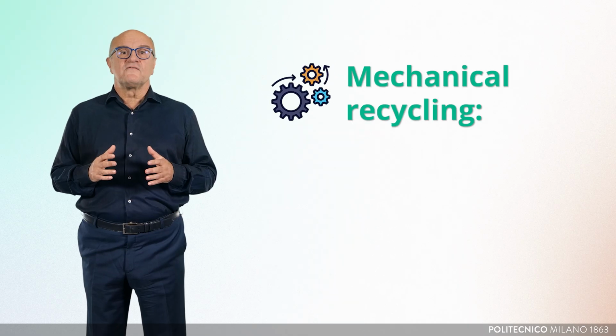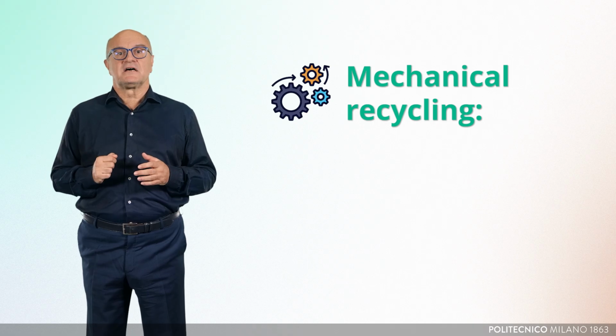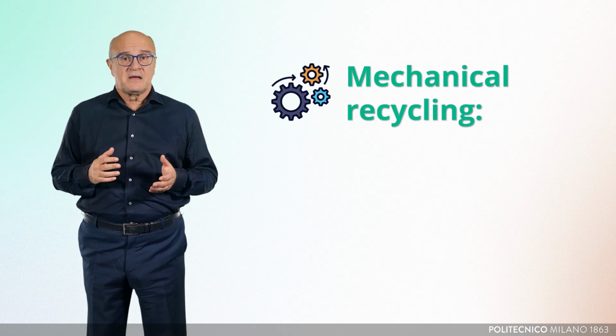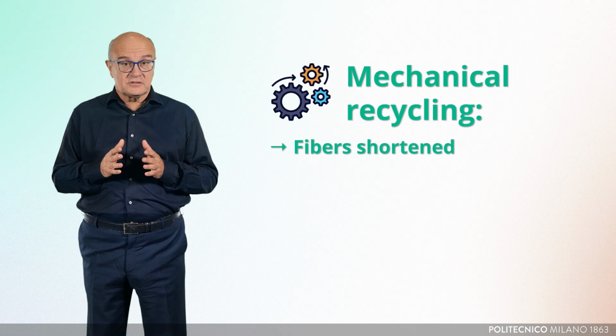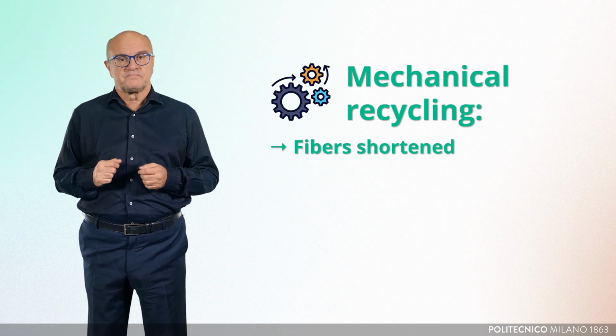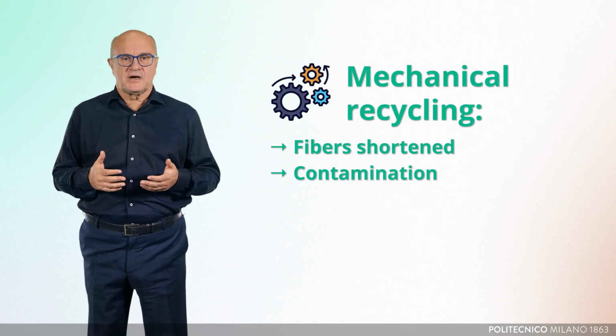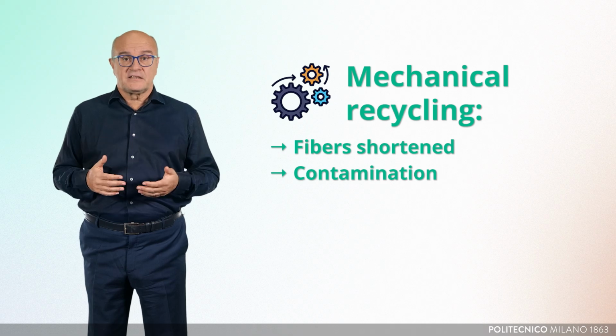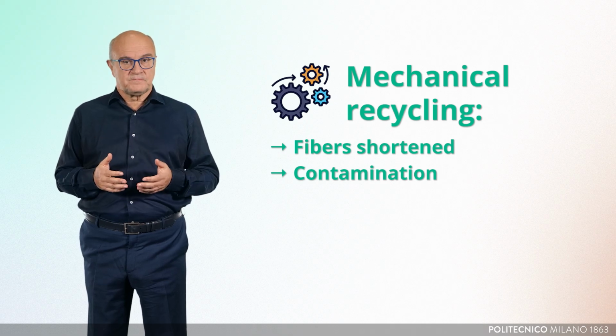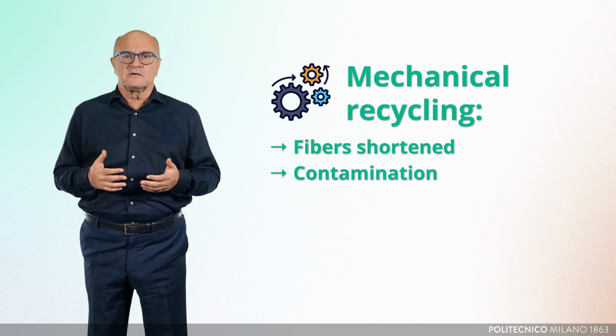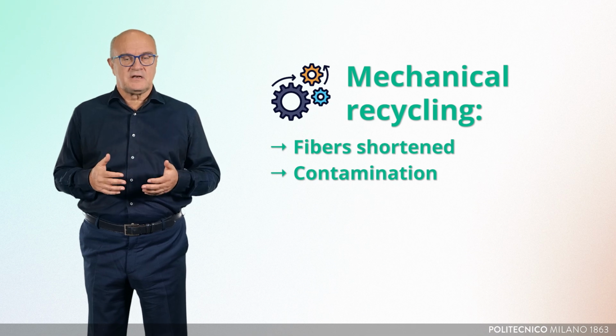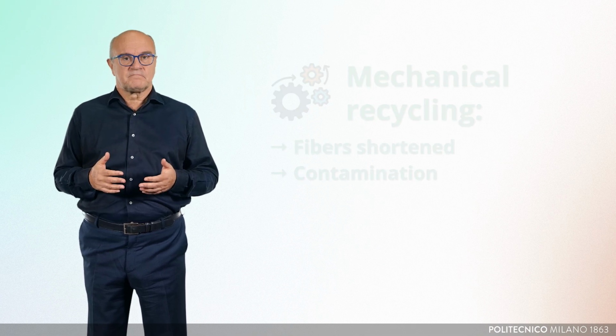The standard technologies for composite recycling nowadays are mechanical and thermal recycling methods. Mechanical recycling involves grinding composite parts into shredded particles, but in this way the fibers are shortened, diminishing their value. Moreover, contamination by resin residues further limits the possibility of reuse. Using this method, fibers are never completely liberated from the matrix.